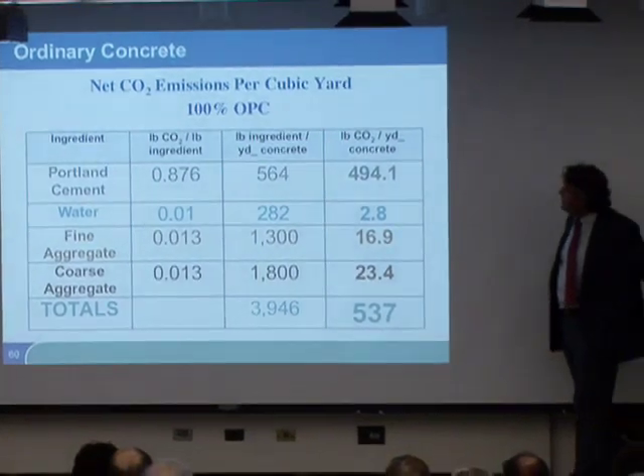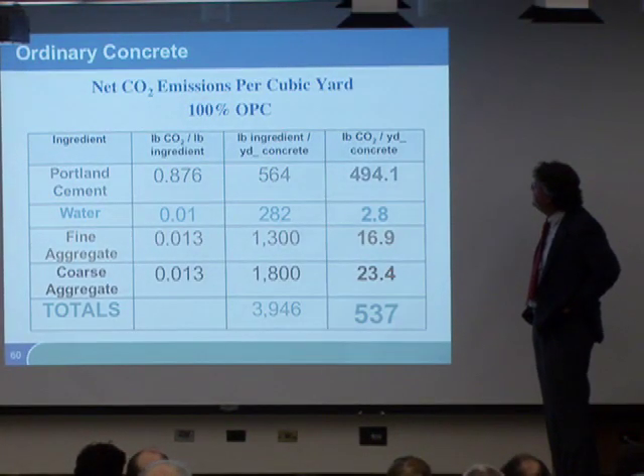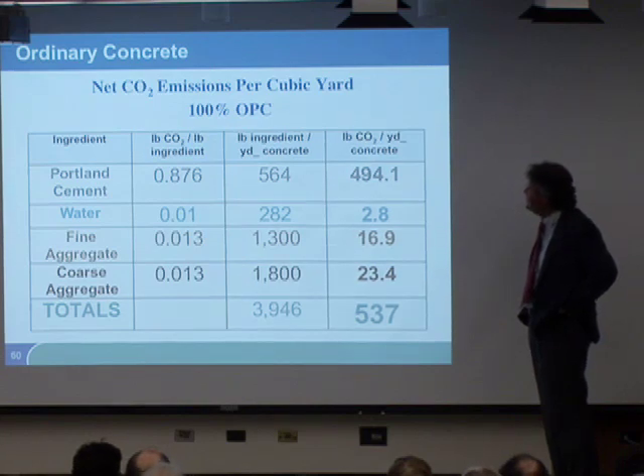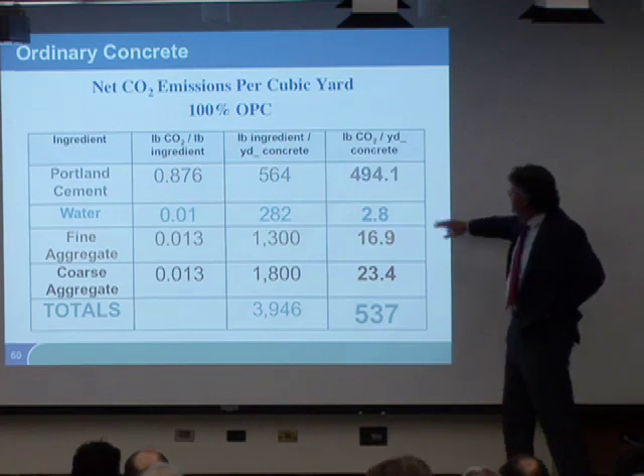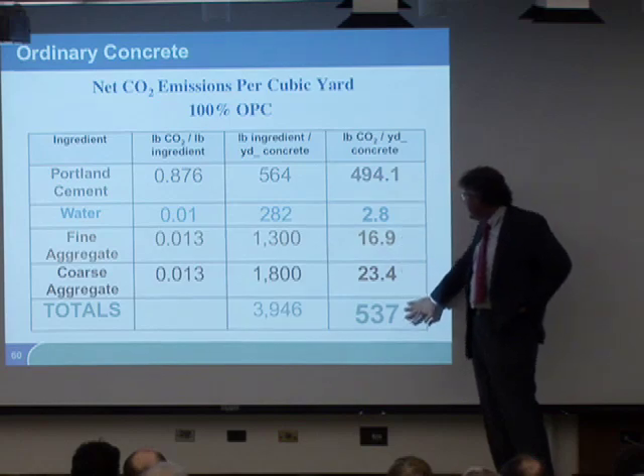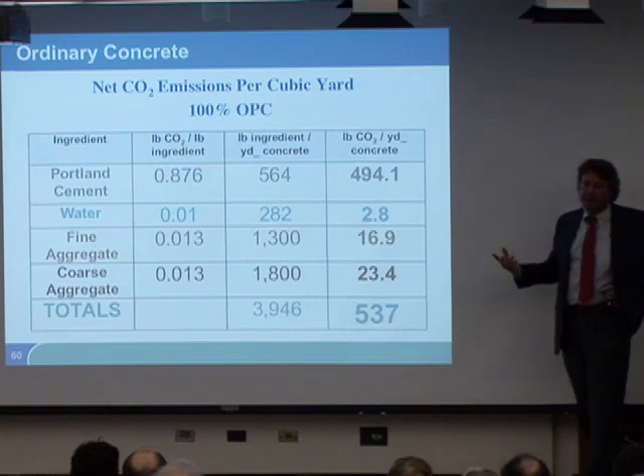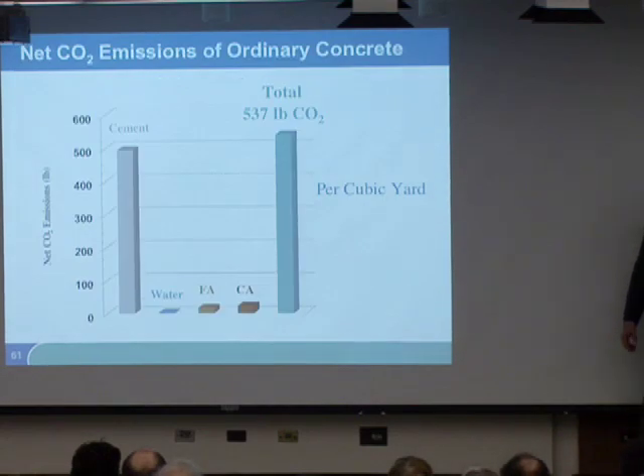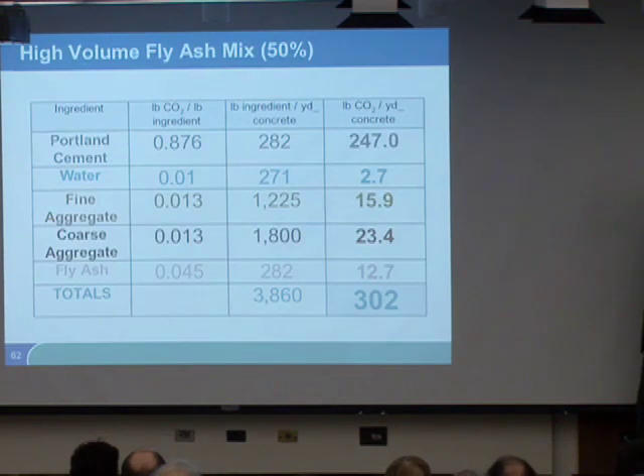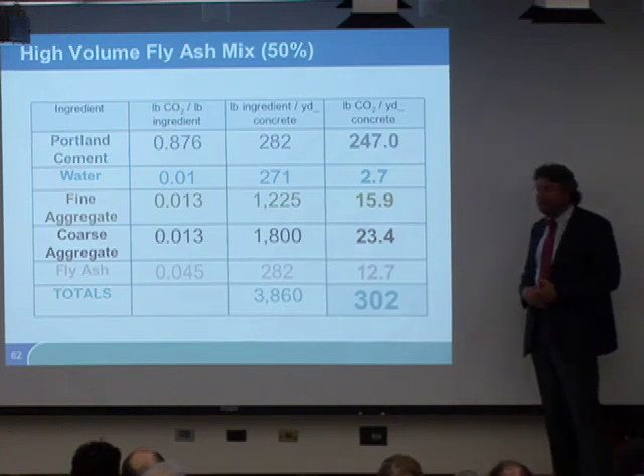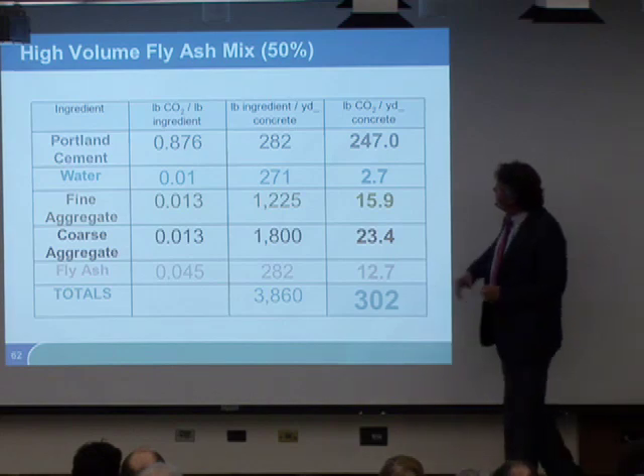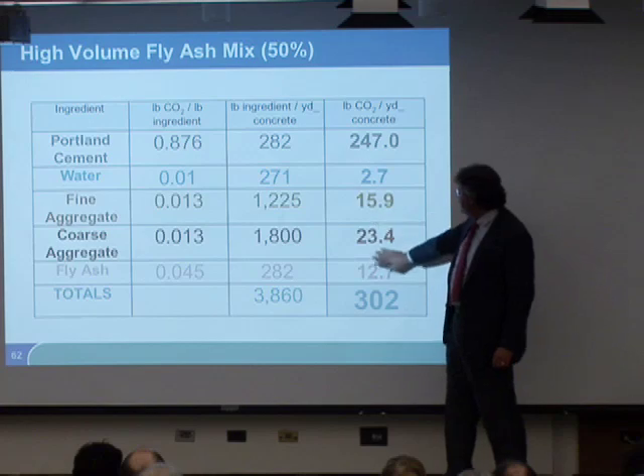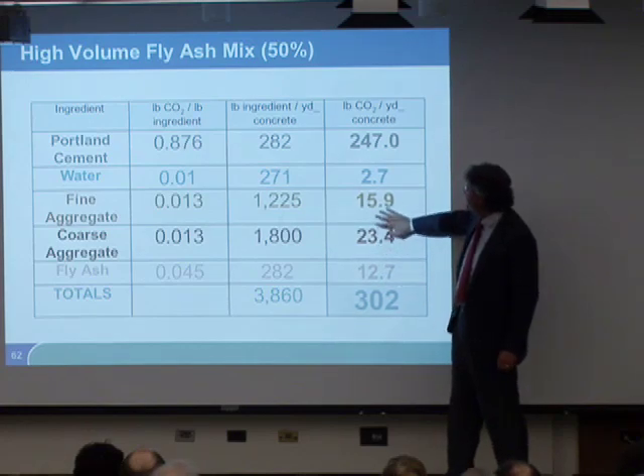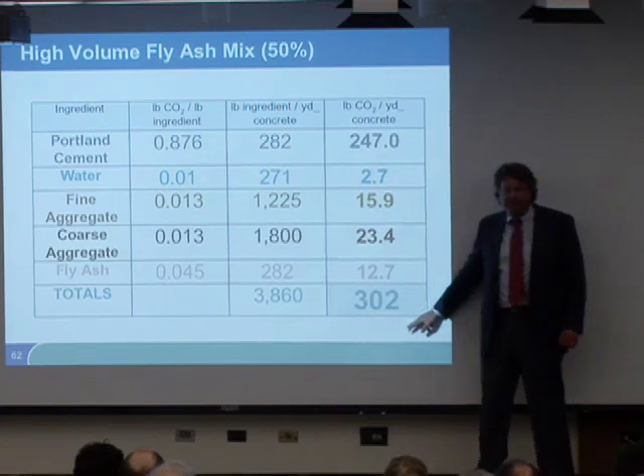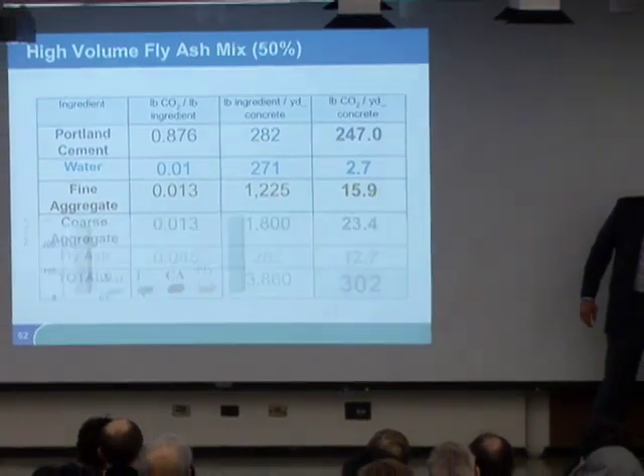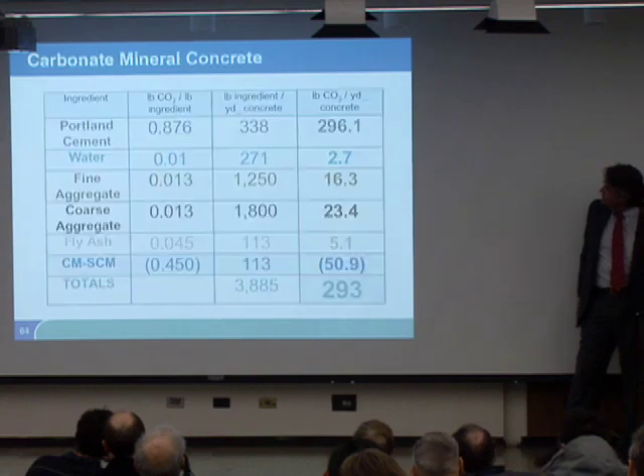Now here's a typical yard of concrete that uses Portland cement. If you take the cement, the water, the sand, and the gravel, you've got about 500 pounds of CO2 associated with that yard of Portland cement. And that's sort of a graphic description of that. If you take the span of the Bay Bridge, which used a 50% fly ash blend, so there's a little less Portland cement, and there's some fly ash in there, in addition to the coarse aggregate and the fine aggregate in the water. And that gets it down to 300 pounds of CO2 per yard. And that's a histogram of that.